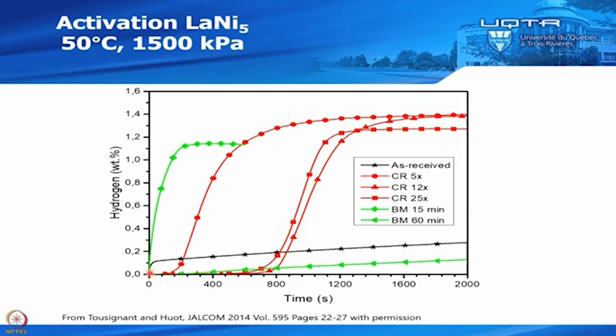The sample is taking hydrogen right away. Okay, but you have a loss of capacity here. But if you ball mill more, if you ball mill 60 minutes, you see that you have a reduction of capacity and the sample is almost dead again. It's even worse than the as cast. But if you do cold rolling, you see 5 times cold rolling.